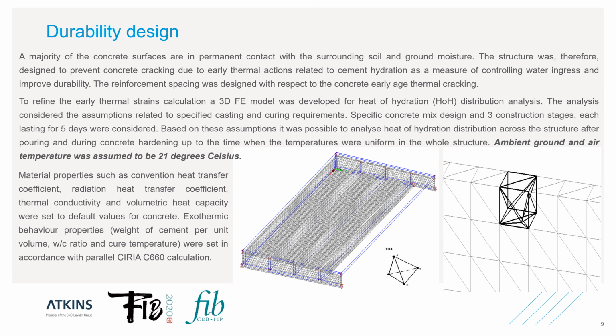As this is a buried structure, the majority of the concrete surfaces are in permanent contact with the surrounding soil and ground moisture. The structure was therefore designed to prevent concrete cracking due to early thermal actions related to cement hydration, as a measure of controlling water ingress and improving durability. The reinforcement spacing was designed with respect to the concrete early age thermal cracking. To refine the early thermal strains calculation, a 3D FE model was developed for heat of hydration distribution analysis. The analysis considered the assumptions related to specified casting and curing requirements.